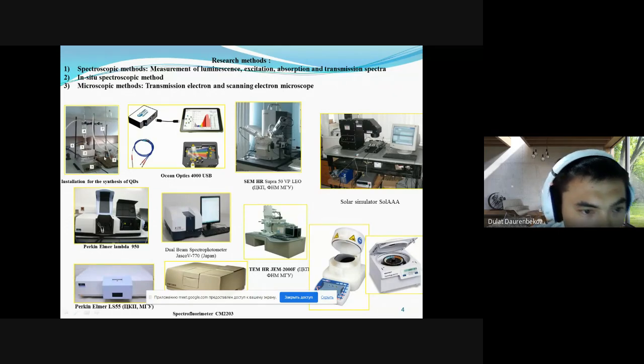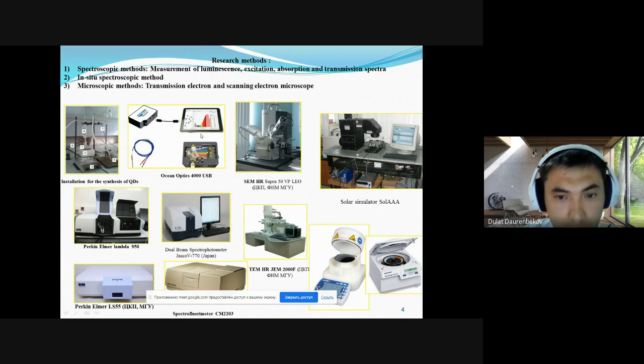This is heating, this is glass, and the heating temperature is about 130 to 250 degrees, and the process goes in an argon atmosphere. Okay, there's an Ocean Optics spectrometer. It's for in situ spectroscopy. As you know, we can follow the process of synthesis online. Online means that while the quantum dots are being obtained, we can see their luminescence by exciting and detecting the luminescence.